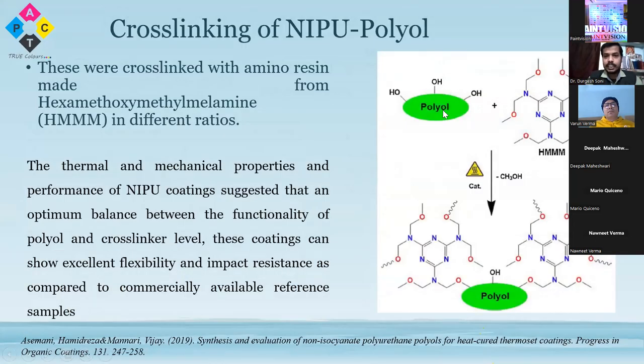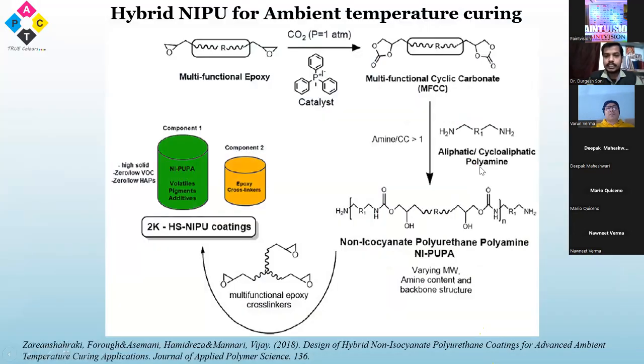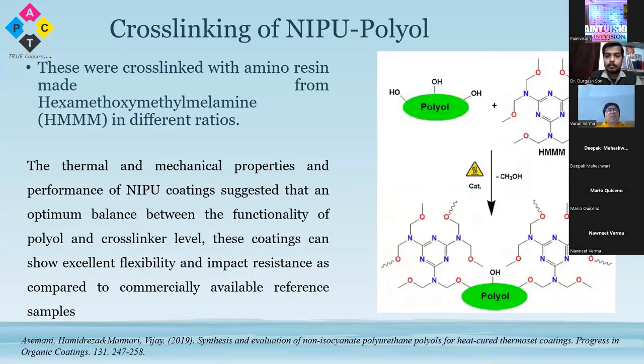After reacting with those OH groups, the films can be cured. In this reaction, we can see this polyol which was synthesized is NIPU polyol. It reacts with the melamine formaldehyde having multiple OH groups. The cross-linking is obtained and we can get the cured polymer, that is 1K thermoset coatings.